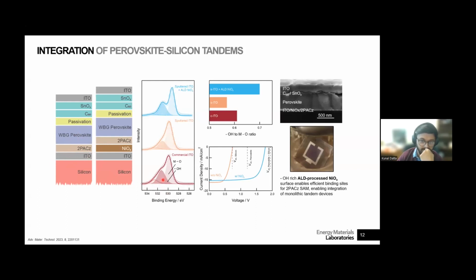So you can look at the oxygen spectrum from the XPS, and you can deconvolute it into two parts. One is the contribution from the metal oxide, and the other contribution is from the hydroxyl groups on the surface. And you can see that this is the commercial ITO, the one that we use for single junction devices, that you have a significant contribution of these hydroxyl groups. But the moment we use the sputtered ITO, this goes down, right? And you can see here the ratio of the hydroxyl to the metal oxide. And as a result, this 2PACz layer wouldn't bind as easily on top of this layer where the hydroxyl concentration is poor. So we added a layer of nickel oxide, processed by ALD, and that increases hydroxyl concentration quite a bit, that you can see here.